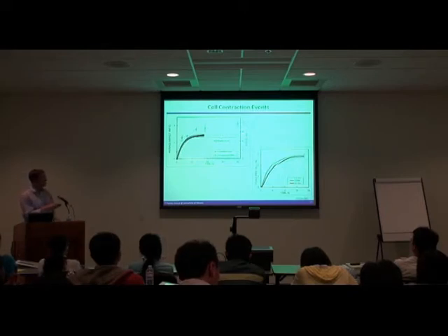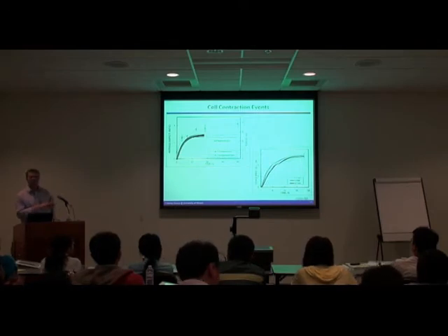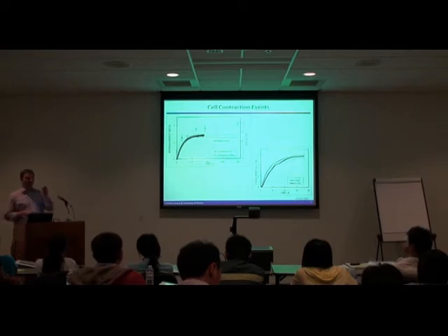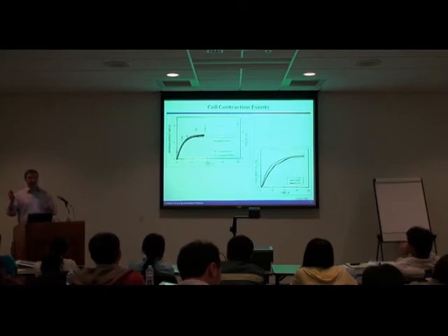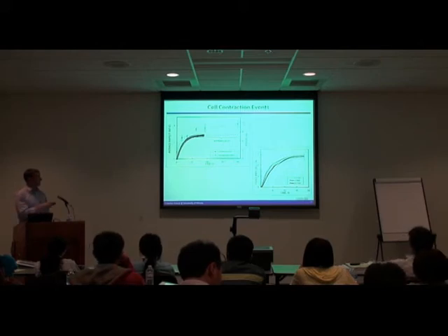nanonewtons per cell. But the other interesting thing is they measured at the exact same time the aspect ratio of the cells. So what they could measure is they could see cells within the scaffold are going from being rounded after being seeded. They're becoming increasingly elongated, expressing higher amounts of alpha smooth muscle actin, and actually having a much more structured cytoskeletal organization than the cells right after originally seeded.